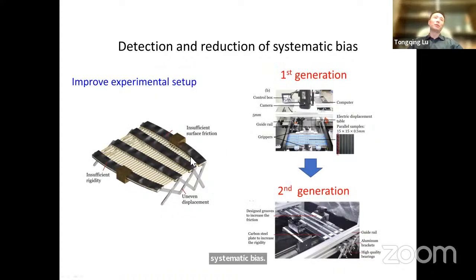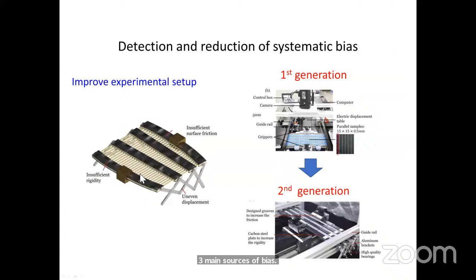However, this method is very helpful for finding the sources of the systematic bias. For example, if you compare this region and this region, and find these two are very close but not close to the middle part, that may indicate the bar is bent. If you compare this row with this row and find they are not close, that may indicate that the displacement applied is not even. So with that, we can now identify three main sources of bias: insufficient rigidity,